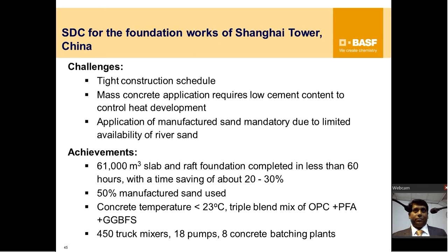You said the concrete temperature less than 23 degrees? It's 23 degrees at the time of pour. After the last pour, it will increase. Why it is 23 degrees at the time of pour is, in a mass concrete, it is well known that the temperature difference between the core and the side should not be more than 20 degrees.